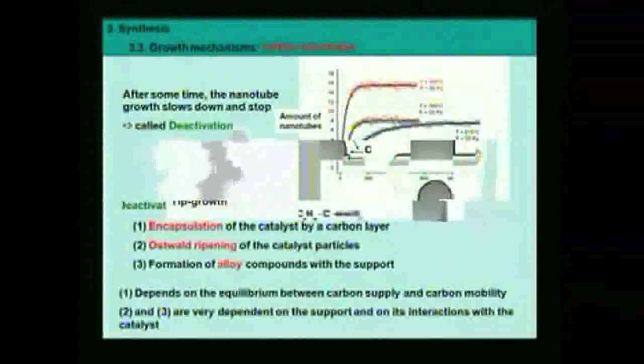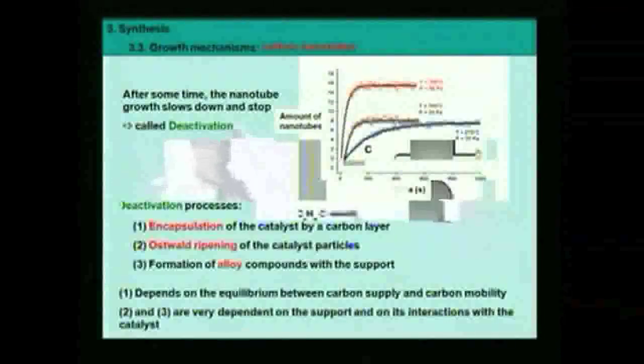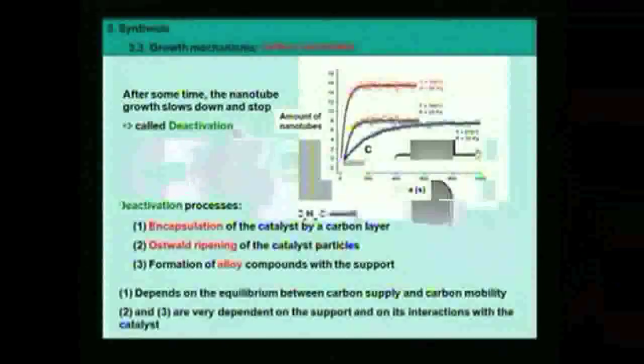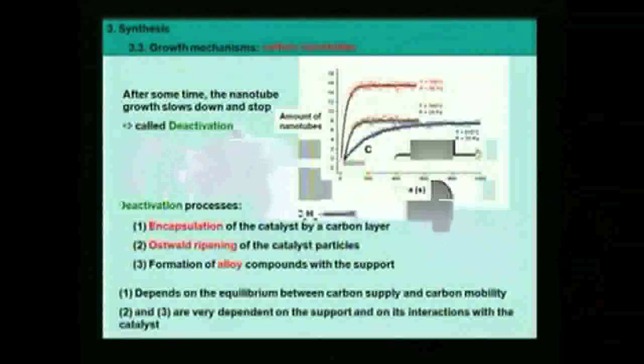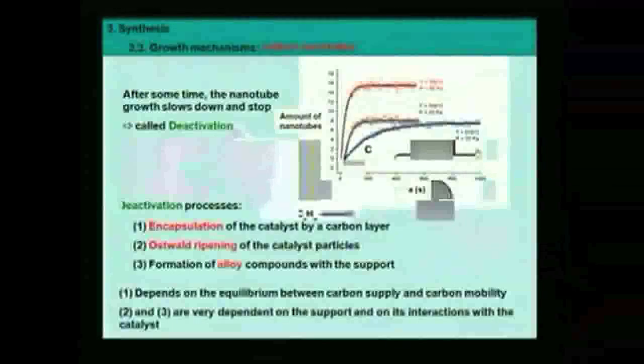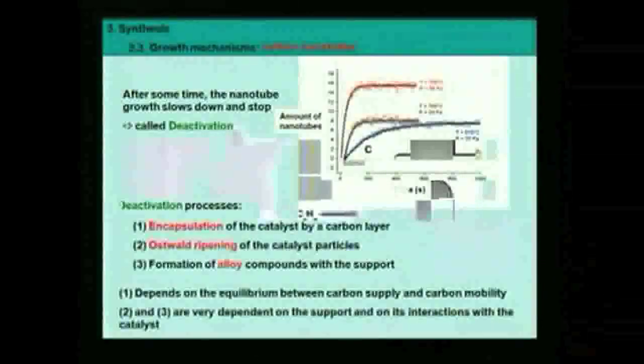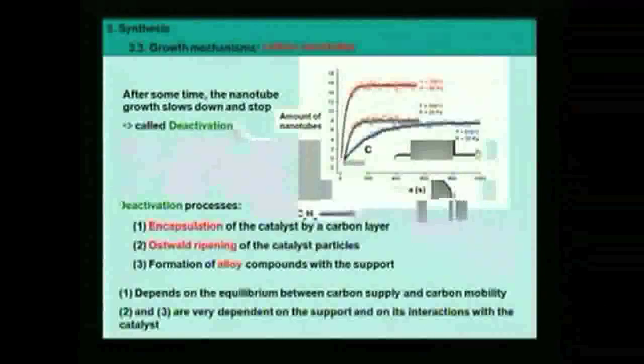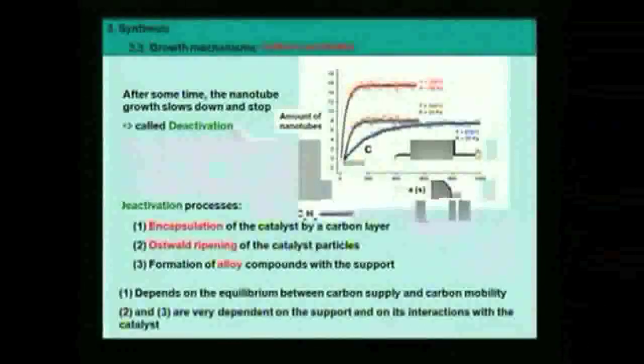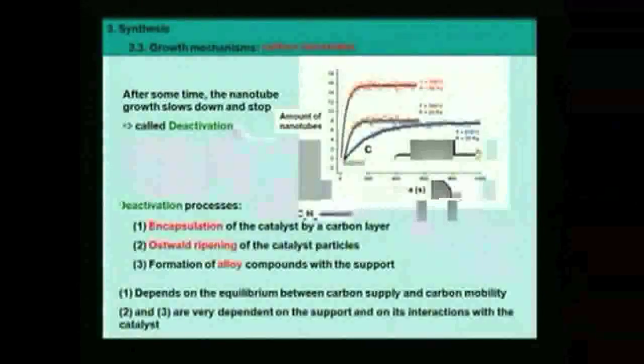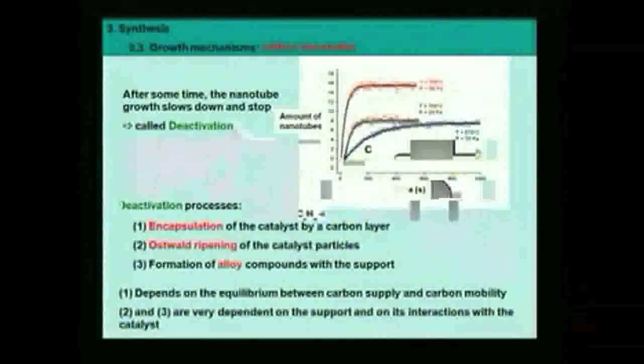Okay, now to finish, we are going to talk about deactivation, which is also an important problem in heterogeneous catalysis: poisoning. This is really important when you do cracking of hydrocarbon molecules, for instance. It's important to say that at first, this is during cracking and reforming of hydrocarbon molecules that those nanotubes were formed. It's very similar, except that in the cracking of hydrocarbon molecules, we want to prevent that because graphitic structures are poison for catalysts.